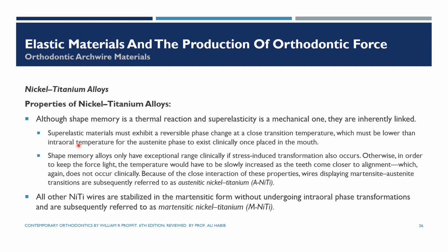For example, superelastic materials must exhibit a reversible phase change at a temperature lower than the mouth temperature for the austenite phase to exist. On the other hand, the shape memory alloys, which are heat activated, should have stress-induced transformation in order to have exceptional range clinically. So these are the two examples.